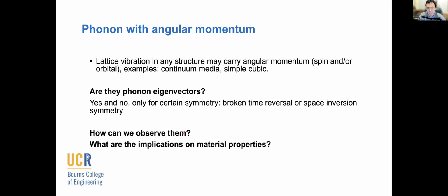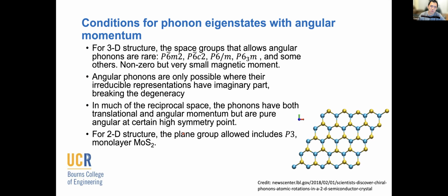So to work on that, we had to find one good material system. It turns out the space groups that allow angular momentum in phonons have to have broken inversion symmetry. There are not that many, at least a few of them. And also, if we look on the pure phonon side, it's impossible to break the symmetry significantly, even if the material is magnetic, because the magnetic moment is actually quite small. So we have to look through those space groups and try to find out which material system works best.